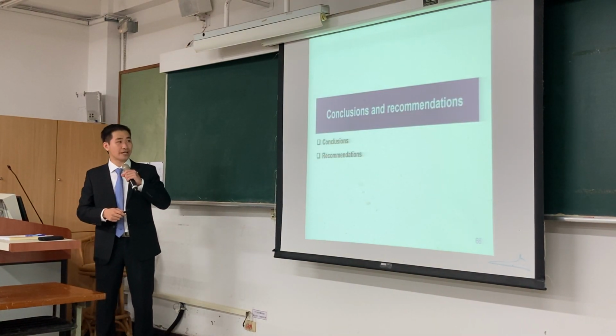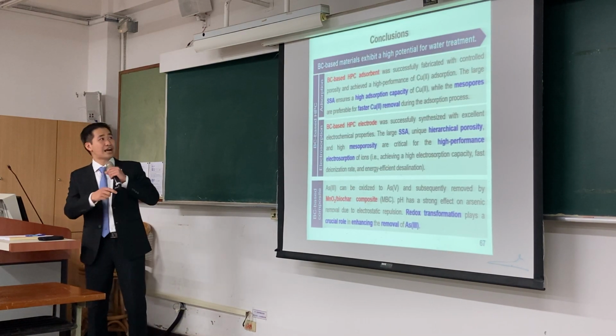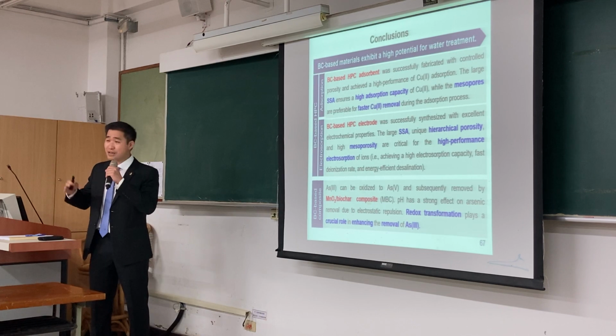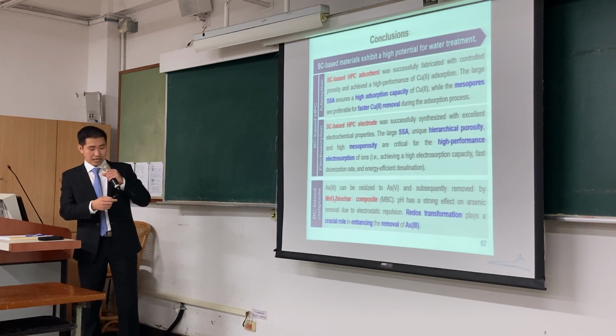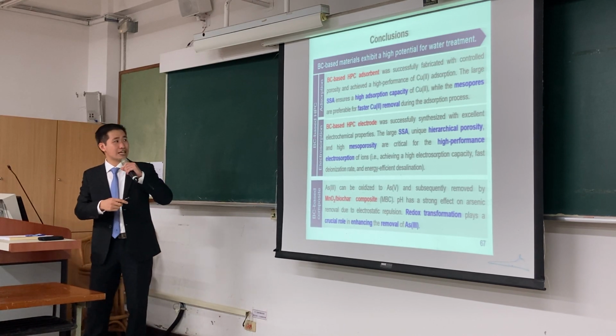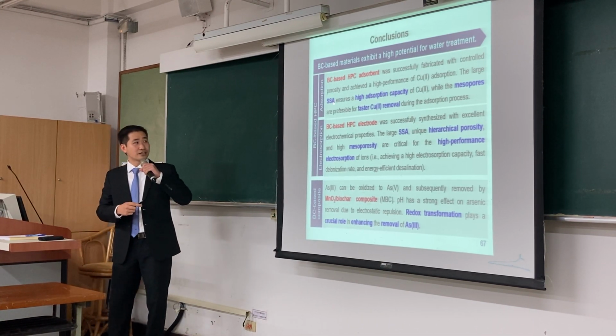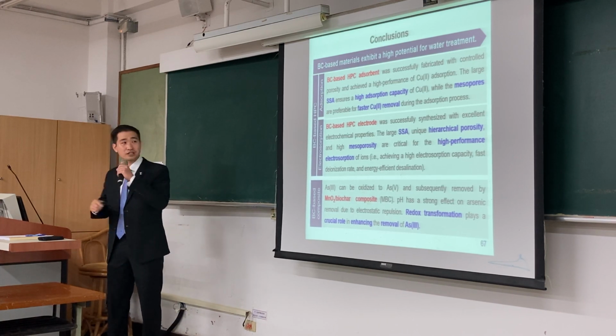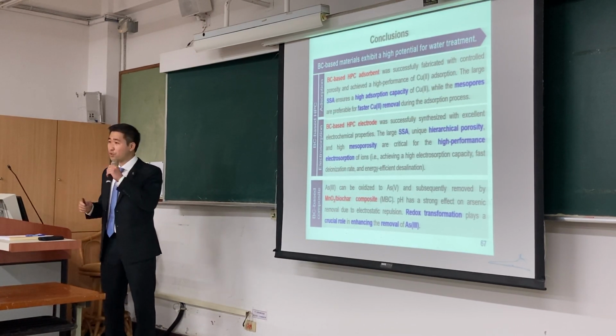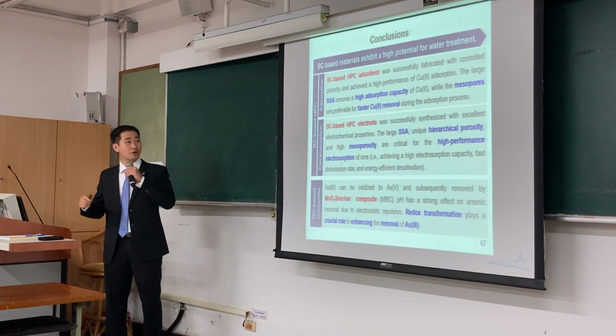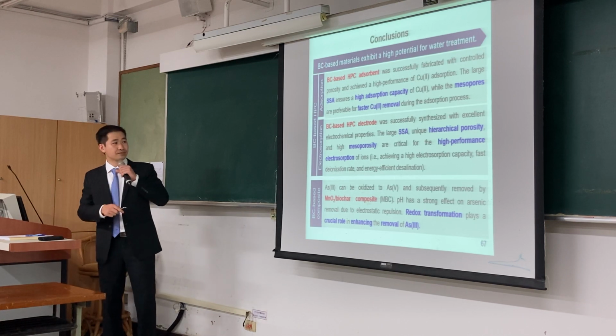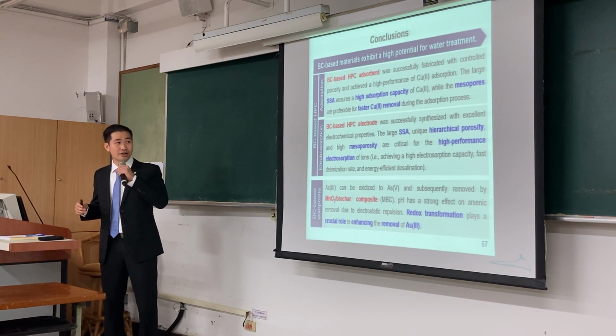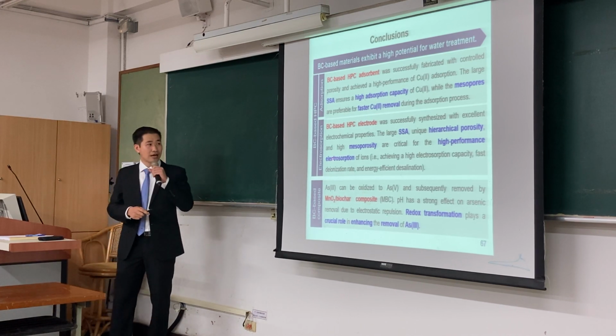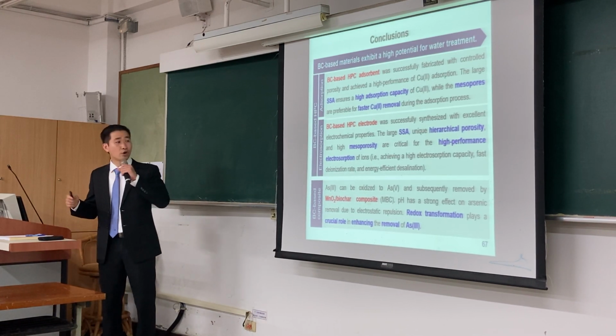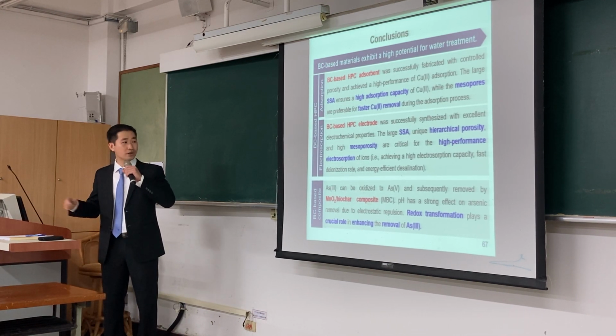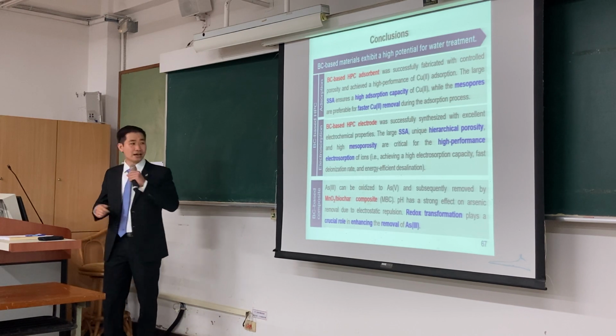Finally, here is my conclusion and recommendation. Firstly, biochar-based material exhibits a high potential for water treatment. In biochar-based HPC adsorbent, specific surface area ensures a high adsorption capacity for copper, while the mesoporosity is preferable for faster copper removal. In electroadsorption, the specific surface area, hierarchical porosity, and high mesoporosity play an important role for high performance electroadsorption of organic ions.